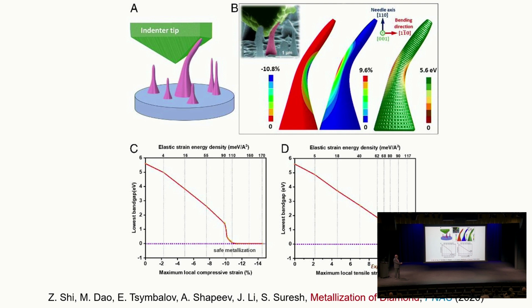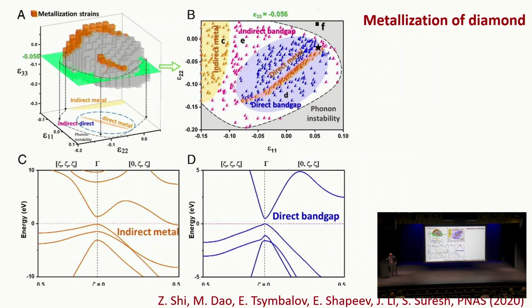And using other calculations, so we use strain energy density, which is strain energy per unit volume, under compressive strain, and we calculate the band gap. In compression, we can go to safe metallization without phonon instability in the case of diamond. In tension, you have to be careful. You could trigger phonon instability if you go beyond this particular strain. But there you can get about 1.2 electron volts, which is very close to silicon. So this has been demonstrated computationally with machine learning. Without machine learning, we couldn't do this.